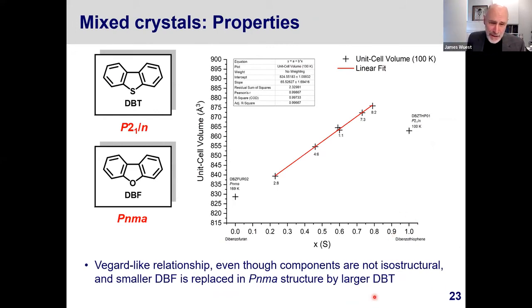What I show you here is a plot of a Vegard law type relationship that shows the unit cell volume of the single mixed crystals as a function of mole fraction of dibenzothiophene. So again, these two materials are not known to crystallize isostructurally. Yet the composition can be varied continuously over a wide range, and the unit cell volume follows a linear Vegard law type relationship. So down here is the dibenzofuran structure.